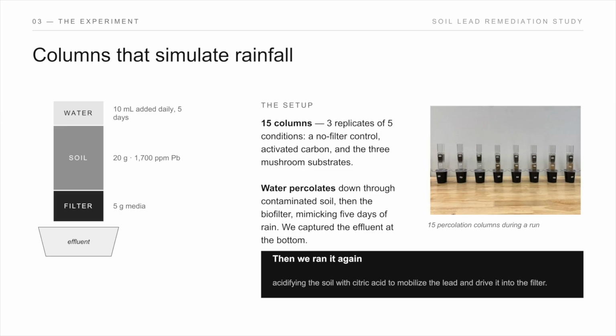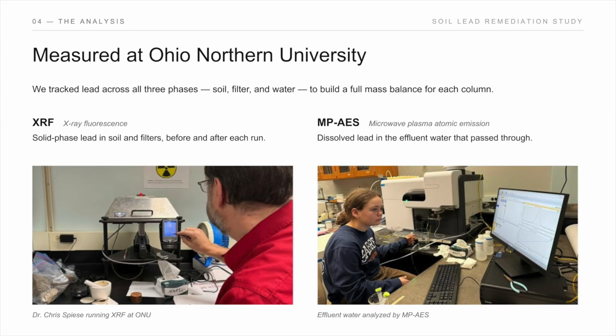So we did another test where we actually increased the acidity of the material, which increased the mobility by about 25 times. So the first big takeaway from the experiment was that by just changing the pH of the soil a little bit, we get a lot more mobility of that heavy metal. And then the next test was the efficacy of the different materials.